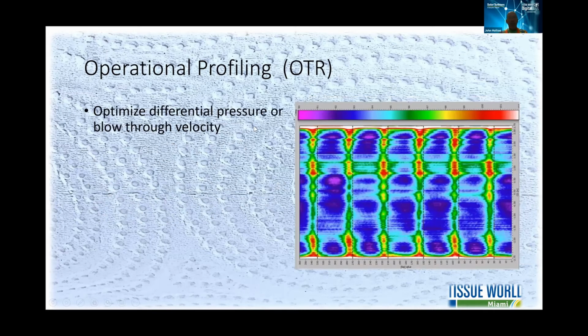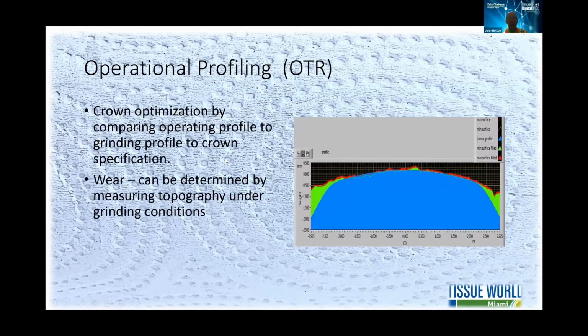Operational profiling is also a way to optimize the differential pressure or blow-through velocity. You can see here in this photo where the headers in this Yankee dryer are clearly visible. This may be an opportunity to optimize the differential pressure or blow-through. Again, this is another operational profile commonly used, and this is for crown optimization by comparing the operating profile to the grinding profile to crown specification. So a good tool for getting the crowns absolutely right.